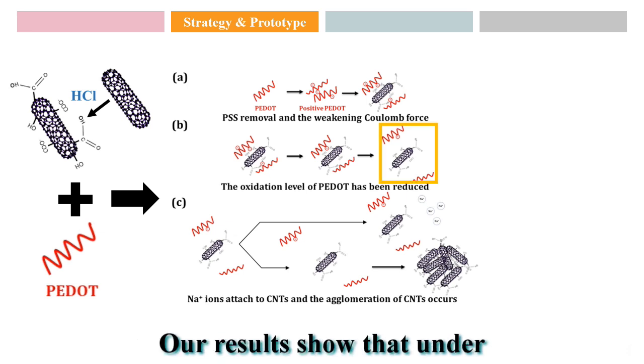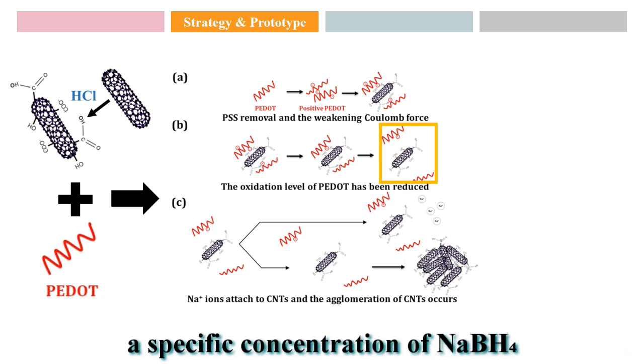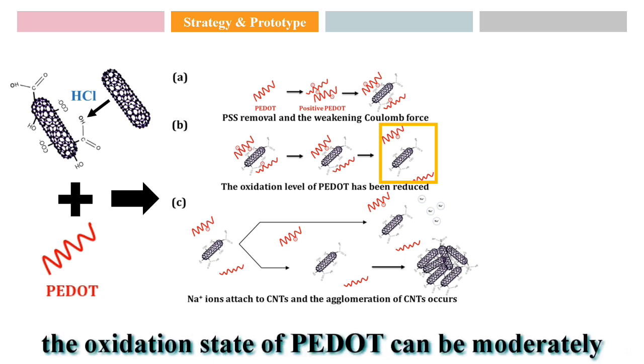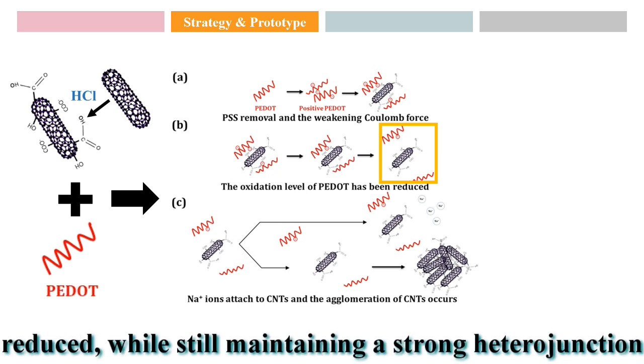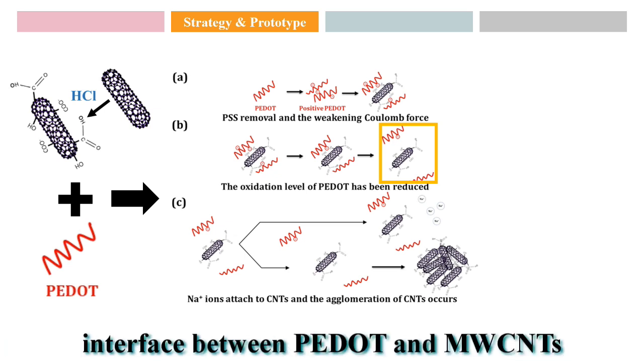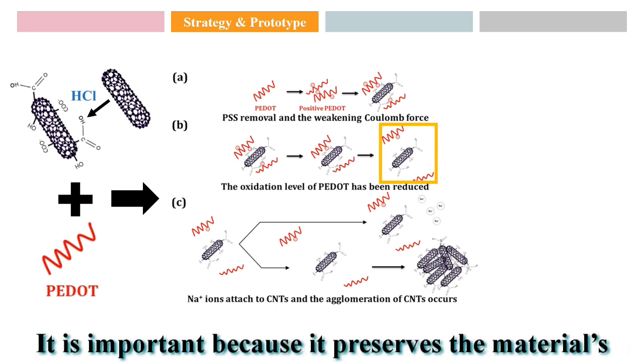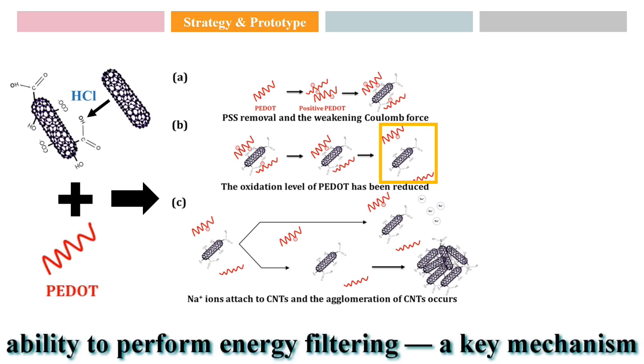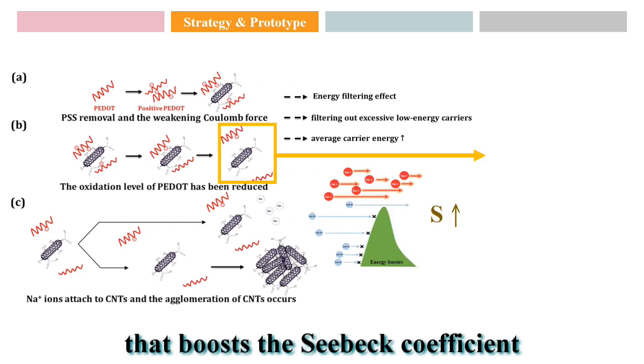Our results show that under a specific concentration of sodium borohydride, the oxidation state of PEDOT:PSS can be moderately reduced, while still maintaining a strong heterojunction interface between PEDOT:PSS and multi-walled carbon nanotubes. It is important because it preserves the material's ability to perform energy filtering, a key mechanism that boosts the Seebeck coefficient.